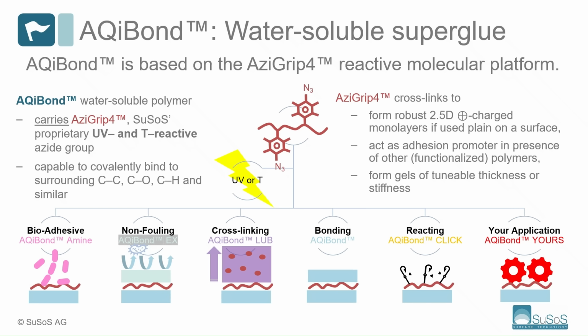Here I would like to introduce to you the AQiBond technology, water-soluble superglue. The AQiBond technology is based on the AziGrip4 reactive molecular platform. So the AQiBonds carry the AziGrip4 SuSoS proprietary azide group. This group is UV and temperature reactive and capable of covalently binding to surrounding C-C, C-O, C-H bonds and similar. And the AziGrip4 group cross-links to form robust monolayers, 2.5D monolayers, if used on the plane surface, and can act as the adhesion promoter in presence of the other polymers, as well as a cross-linker to form gels of tunable thicknesses or stiffness.